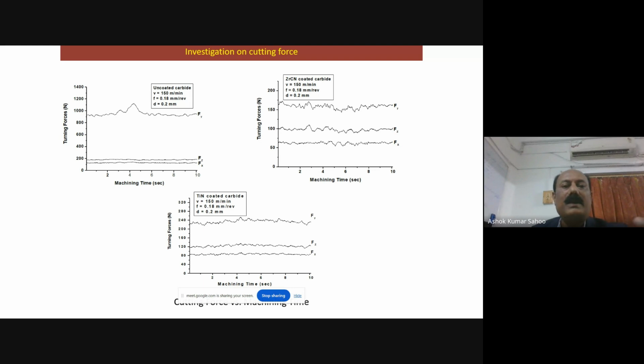Fy component is higher, but in comparing the uncoated carbide and the coated carbide insert, we can see the titanium nitride coated carbide insert induces less cutting force as compared to the uncoated carbide insert, where the cutting force is nearly 900 to 1000 newtons. This is responsible for chipping and breakage of the cutting tool material due to the higher cutting force in machining of hardened D2 steel, whereas for the titanium nitride coated carbide insert the cutting force is around 160 to 240 newtons. So it's comparatively safe. That's why the life of the cutting tool for the coated carbide insert is usually higher as compared to the